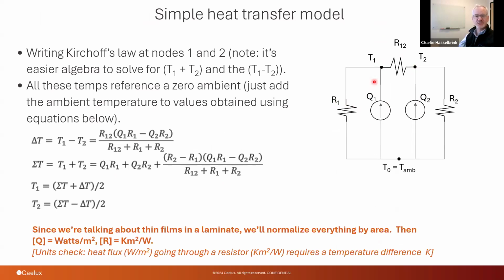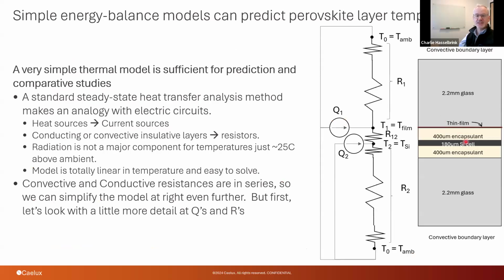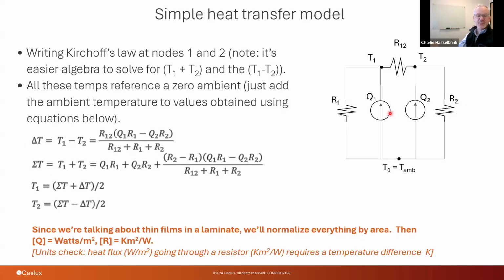There is somewhat lower resistance on the front surface of the panel because there's no encapsulant on this side, but here there's an encapsulant, glass, and convective. And from the thin film, there's only glass and convective. But this encapsulant's thermal resistance is not very significant compared to the convective boundary layer. Again, it's dominated by these resistors here on the end. So basically, these two resistors are about the same, and this resistor is actually quite small. And so as a result, you might expect these two temperatures not to be too different.